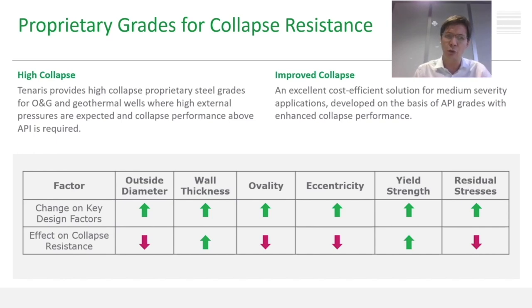But let me show you on which parameters we can act in order to improve the collapse performance of our pipes. The collapse is influenced by different key design factors. Some of them are not under our control as a pipe manufacturer. The outside diameter: increasing the outside diameter reduces the collapse resistance. But this is not under our control, as it is already defined by the well design. The same happens for wall thickness, which on the contrary, when increased, will improve the collapse resistance.